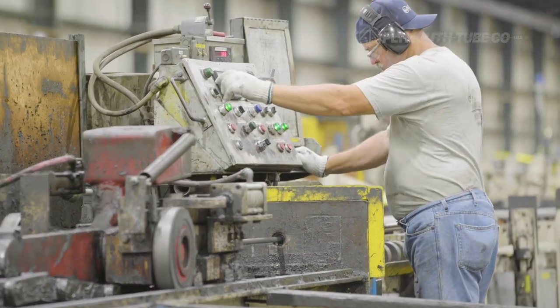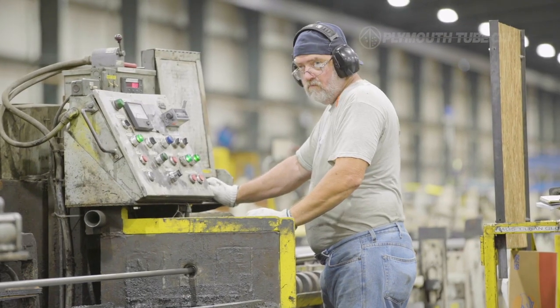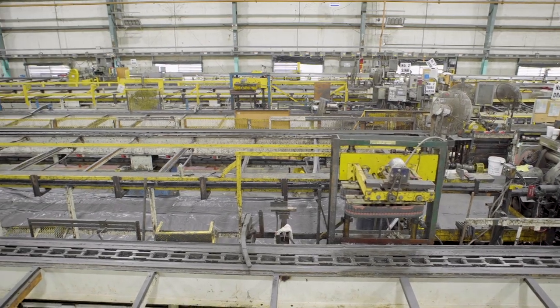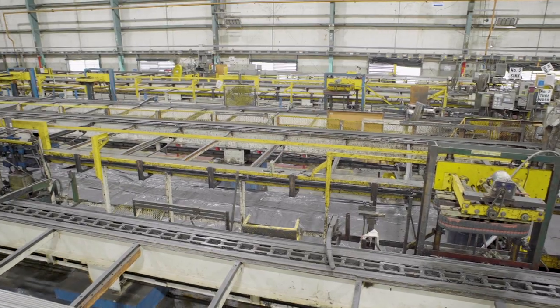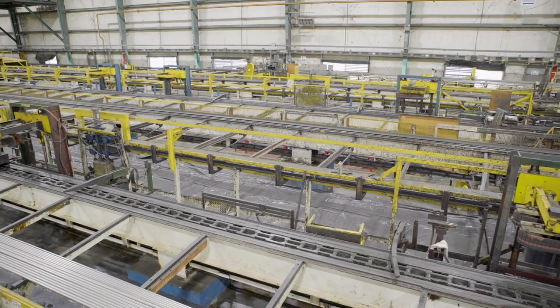Size capabilities. Create sizes that aren't attainable otherwise. Very heavy or very light wall welded tube can be made by starting with a larger diameter tube and drawing to the final size. This allows the use of thicker or thinner walls than possible with roll forming and welding. Higher strength. Most stainless steels are not heat treatable for higher strength. For many applications, such as mechanical or aircraft applications, stainless steel tubing is cold drawn to raise the tensile and yield strength. In some cases, the yield strength may be 3 times the annealed value. Cold reduction also eliminates the need for OD polishing.